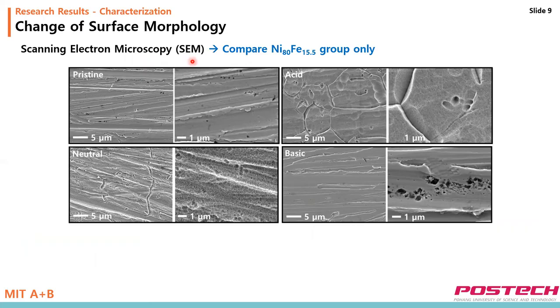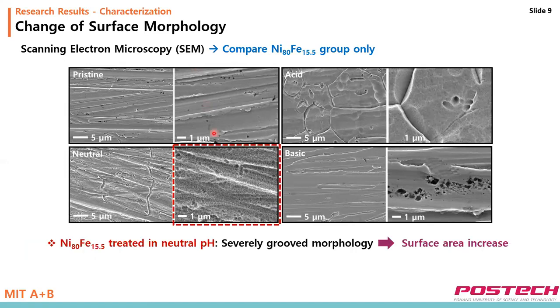First of all, only the treated nickel-rich base material group was evaluated. Using scanning electron microscopy, variation of morphology was observed. When treated at neutral pH, severely grooved morphology were clearly observed. This results in an increase in surface area that can offer more active reaction sites.